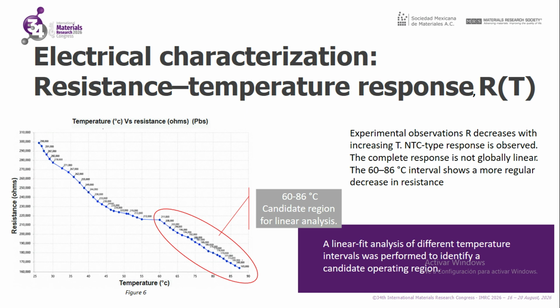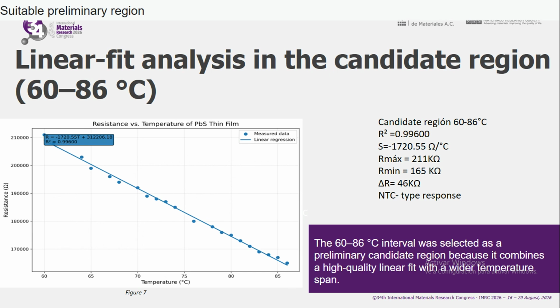Electrical characterization, resistance temperature response, RT. In the graphic of figure 6, the zone marked in red shows experimental observation: resistance decreases with increasing temperature. An NTC-type response is observed. The complete response is not globally linear. The 60 to 86 degree interval shows a more regular decrease in resistance. A linear fit analysis of different temperature intervals was performed to identify a candidate operating region.